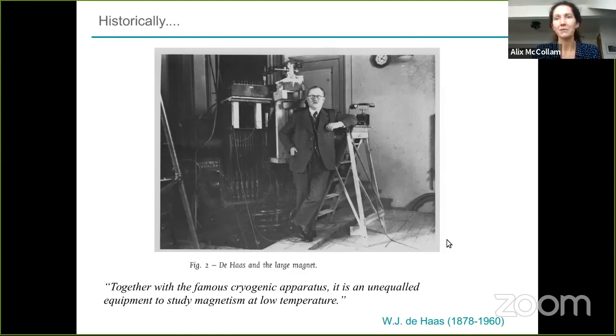Susceptibility measurements are relatively straightforward, but things like neutron, I mean, I didn't talk about measurements like X-rays or neutrons that give us things like the dynamical susceptibility or the spectral function if you're thinking about optical conductivity or X-rays perhaps. And these are things that at the moment, we don't have them established in the high magnetic field laboratories, but in Toulouse, for example, they've developed a sort of mobile high magnetic field magnet. It's a pulse magnet that they can move around, and this can be taken to places like the ILL, and then you can actually do very high pulse field experiments with the neutron scattering setup. Now it takes a lot of time.